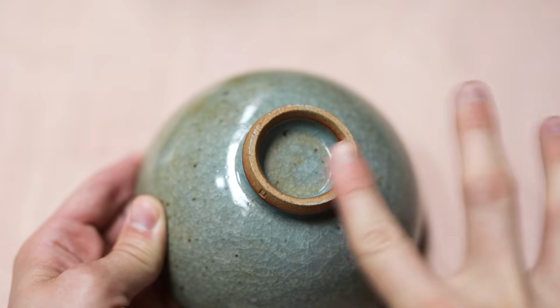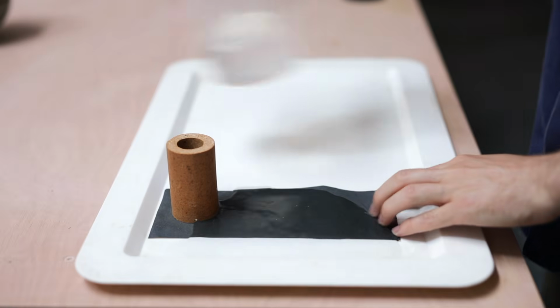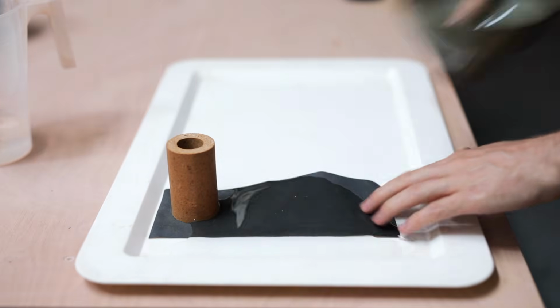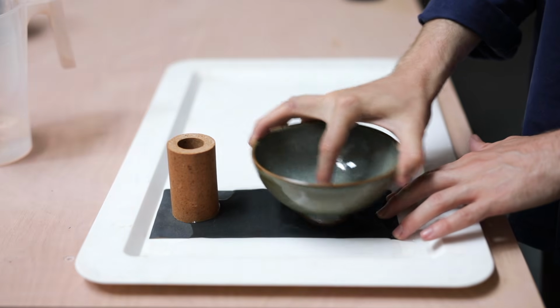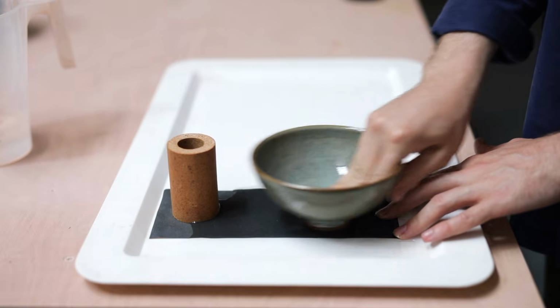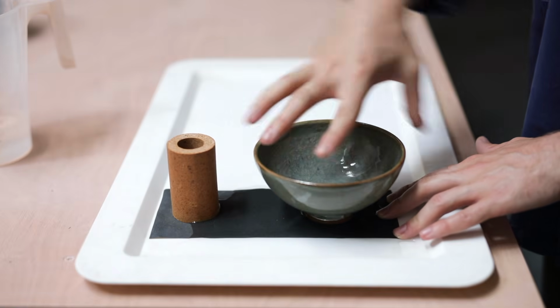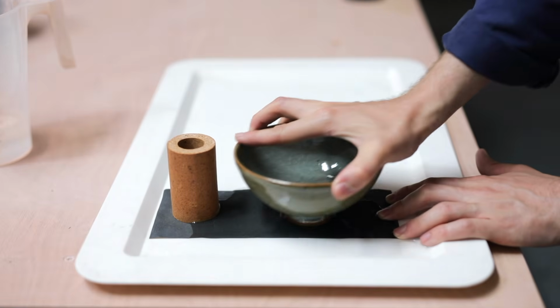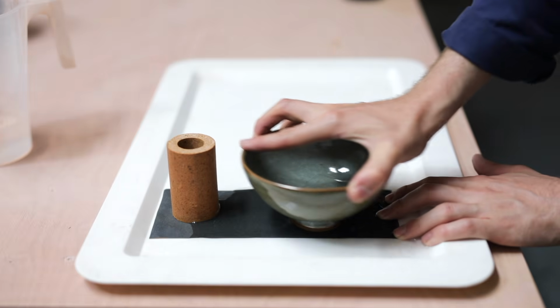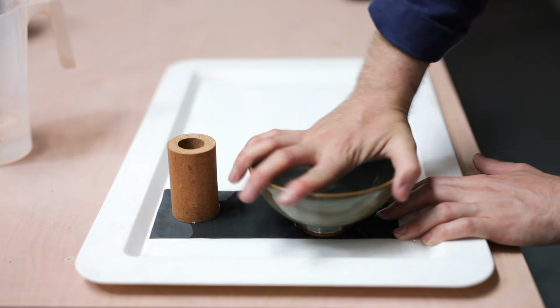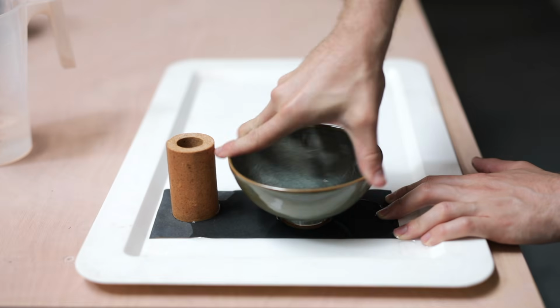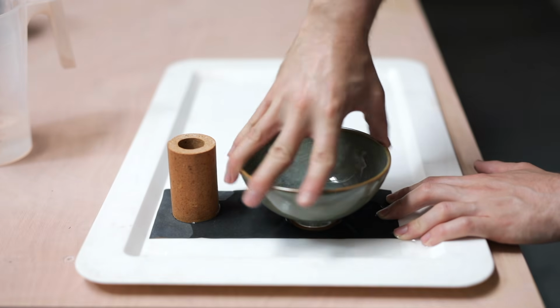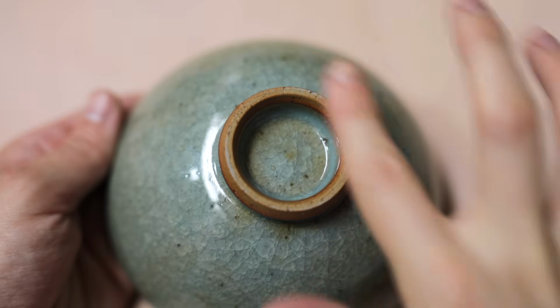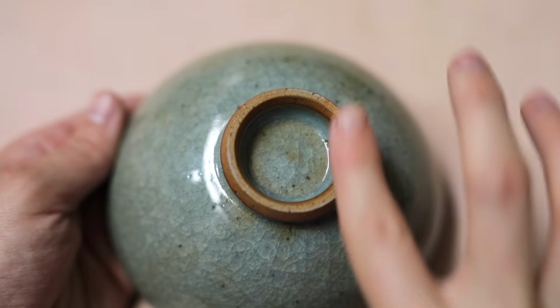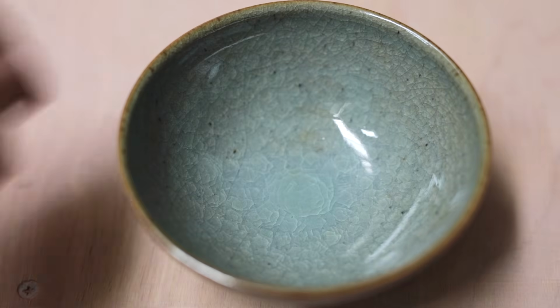To polish the foot rings of these bowls, I just soak some wet and dry sandpaper and carefully grind the pot in place for a moment or two. I don't want to sand them too much, as I quite like the contrast between smooth glaze and rough clay. Equally, if I polish away too firmly, I'll remove the nice flashed colour on the surface of the clay, which the reduction firing provides. And with that, the pot is finally properly finished.